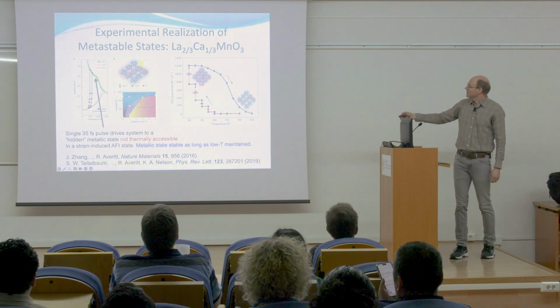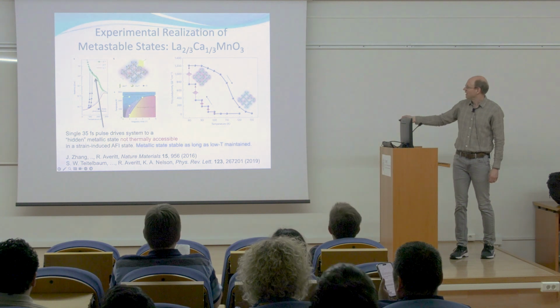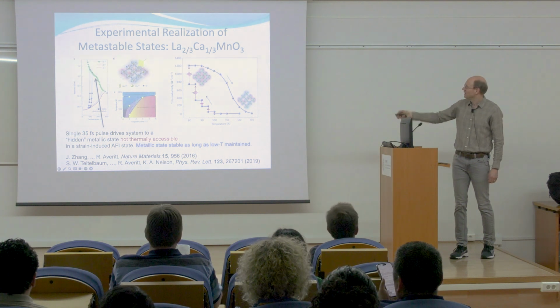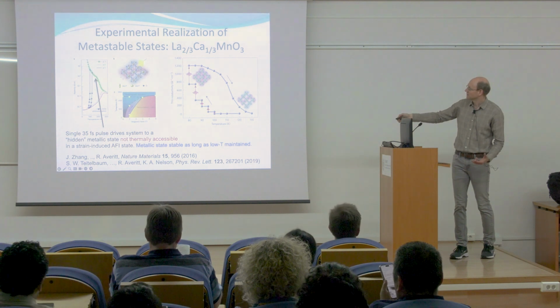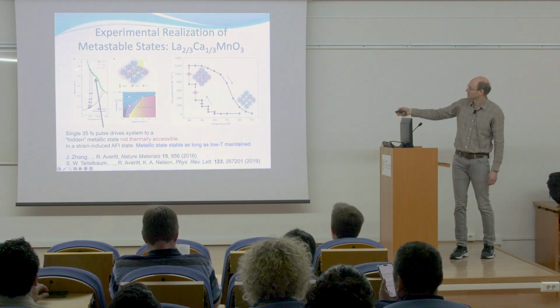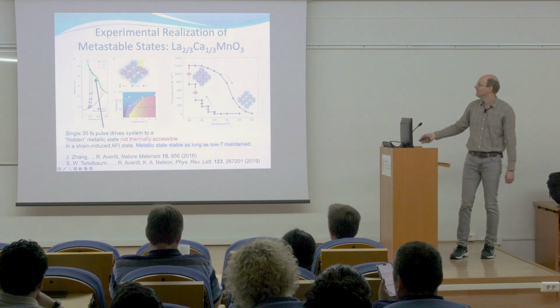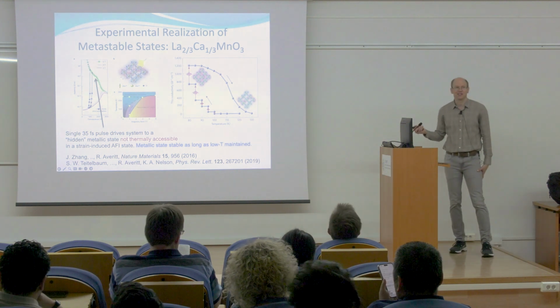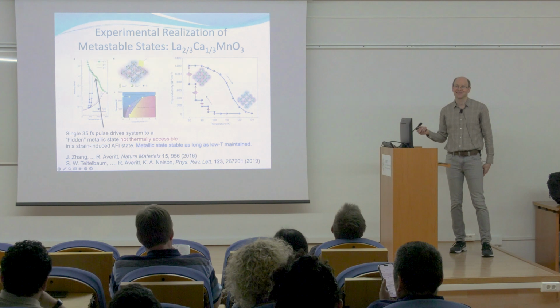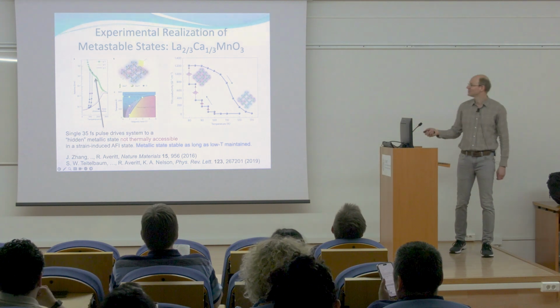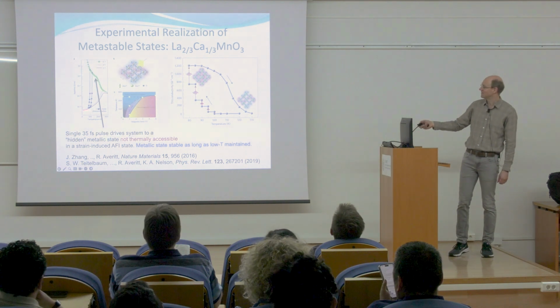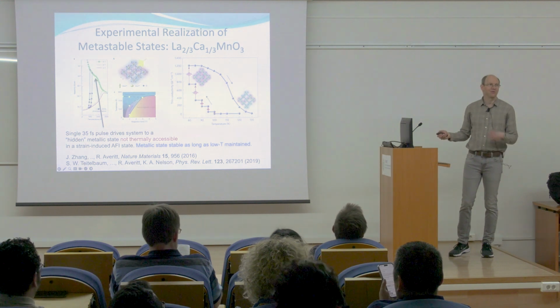So, and then this system recovers on a long time scale, which depends on the temperature that you hit it with a pulse of light. The lower the temperature, the longer the time scale. Here, the time scale is actually weeks. So that is a totally different thing than minutes. So in this system, this metastable metallic ferromagnetic state will last for weeks.